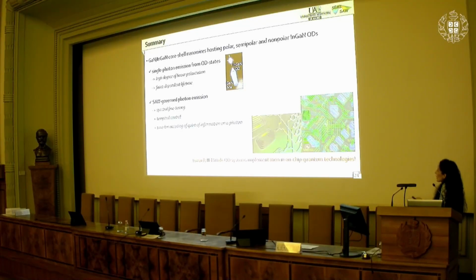What I have shown here is that we can generate single photons, which are highly linearly polarized, by using gallium nitride quantum dots that are grown on polar, semipolar, and non-polar facets of epitaxially grown gallium nitride nanowires. And I have also shown that these quantum dot states are quite sensitive to propagating acoustic fields, and that this can be used as an effective method for the in situ control of the photon emission wavelength and its emission time. And by combining these two, we are basically able to encode qubits of information onto the photon emission time. So this, of course, is quite important for the integration of such quantum dot systems into future on-chip quantum technologies.